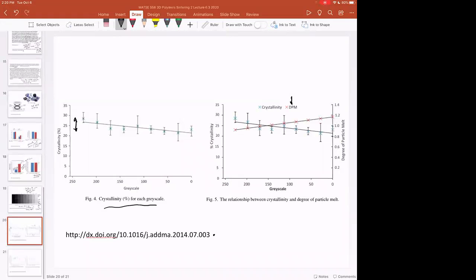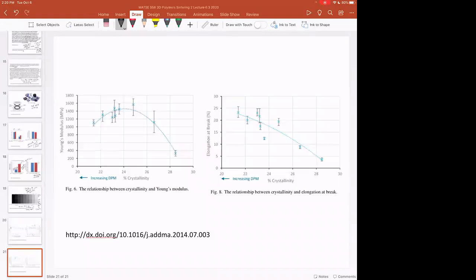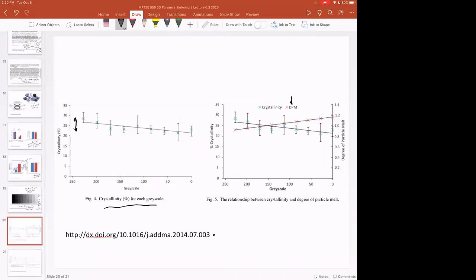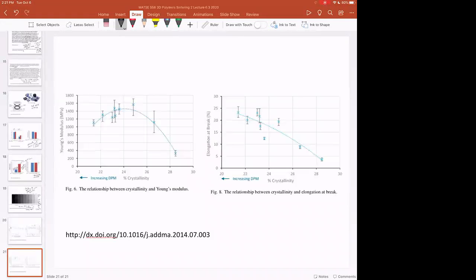So the one real issue that you have is that even though the crystallinity changes a little bit, you see that the mechanical properties can change a lot. Now, for high crystallinity samples, what they've shown is that in general, you have lower Young's modulus. So this is too much crystallinity because you have a lower degree of particle melting versus something that has less crystallinity.